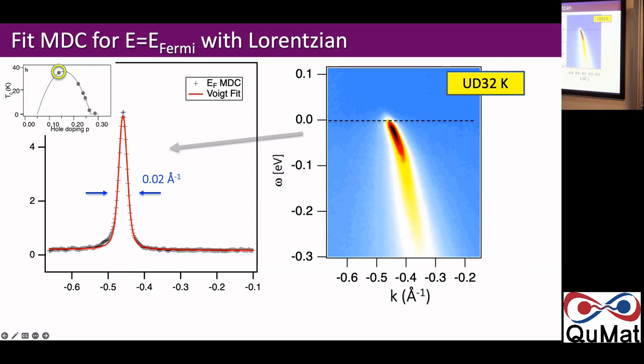Can we call this one a quasi-particle, like a broadening itself? Very quickly, the half width of this object translated into energy terms is larger than its energy. So in the Landau definition, no. The other extreme theoretically is the holographic one, which says there are no particles, let alone quasi-particles. That's valid for this particular doping level up here, where the TC is maximal. So it's a sticky wicket, to use an English expression from cricket. When do you call this thing a quasi-particle, and when don't you? That's a really hard quantitative judgment, for which you need very, very good experimental data.